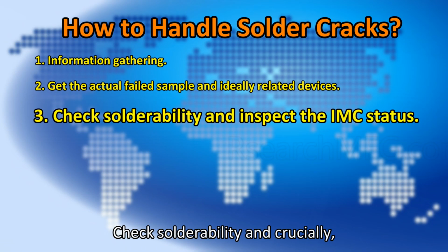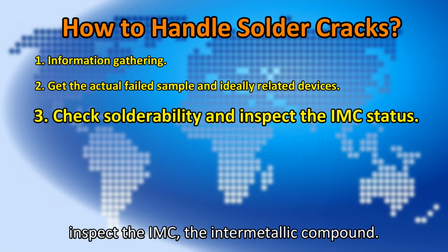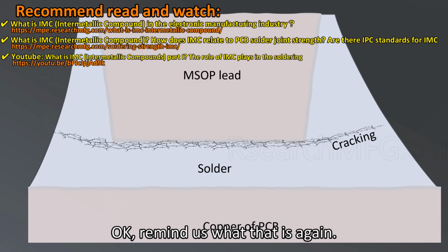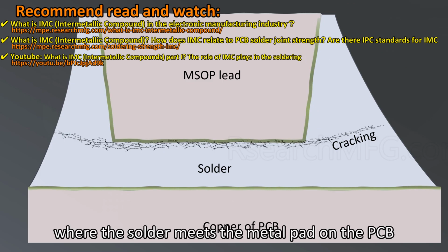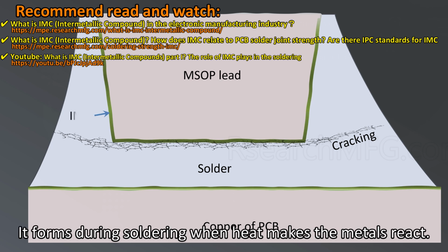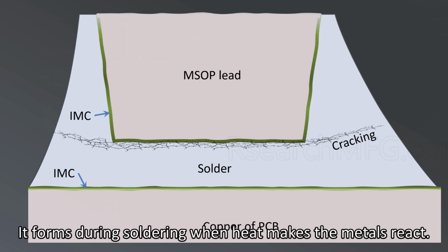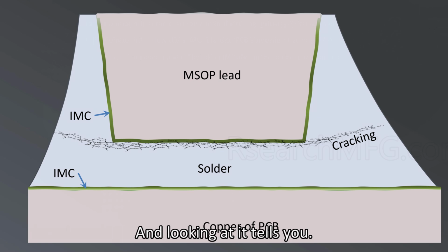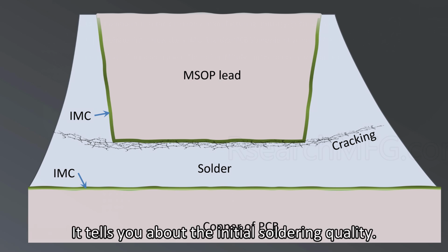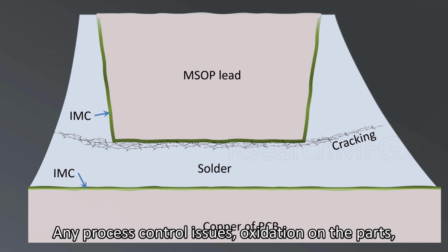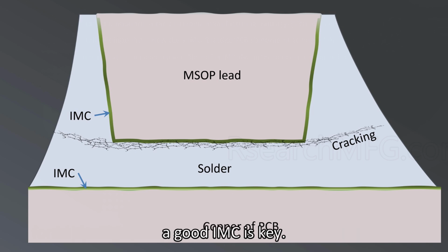Step 3, check solderability and, crucially, inspect the IMC, the intermetallic compound. IMC. Okay, remind us what that is again. It's that thin layer that forms right where the solder meets the metal pad on the PCB and where it meets the component lead. It forms during soldering when heat makes the metals react. And looking at it tells you? It tells you about the initial soldering quality. Was the reflow profile right? Any process control issues? Oxidation on the parts? A good IMC is key.